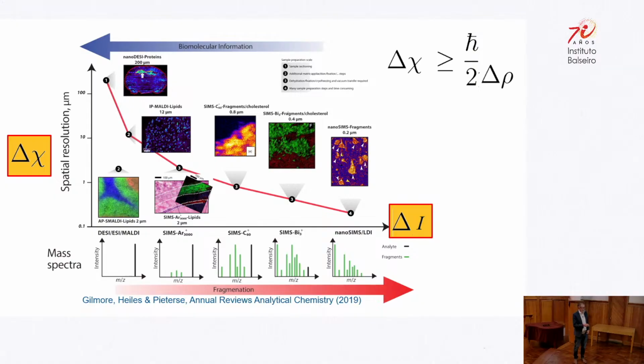But the types of ion beams that we use that can achieve very high spatial resolutions, down at about 50 nanometers, unfortunately cause a lot of fragmentation, and hence we have a lack of confidence in what that molecule is. At the other extreme, we have techniques which have a very broad beam, but they cause very little fragmentation. So now we know exactly what that molecule is because we haven't fragmented it, but we've got very poor spatial resolution, hundreds of microns. So everything I'm trying to do is find how far we can push this curve down to get better spatial resolution and better confidence in the identity.